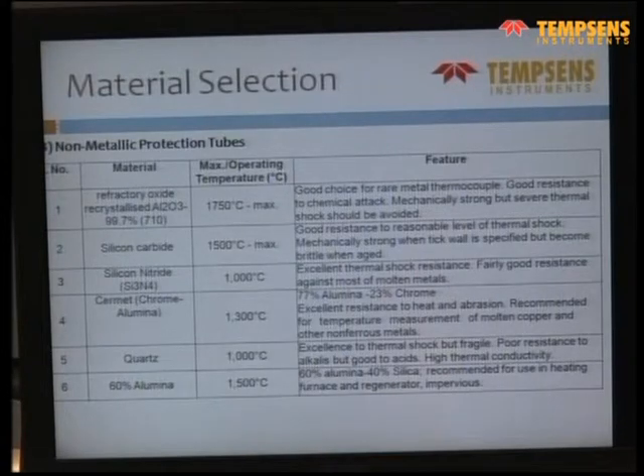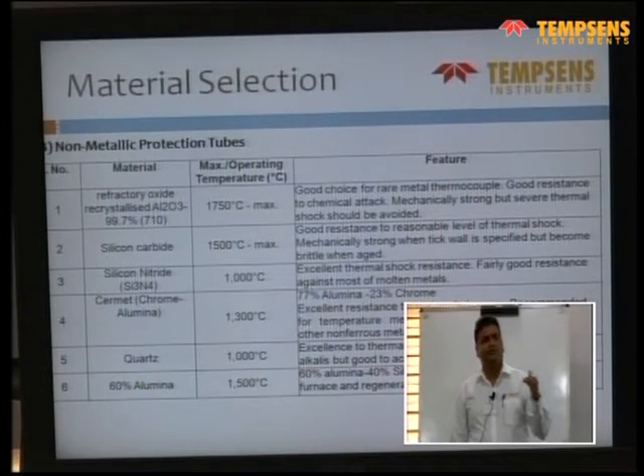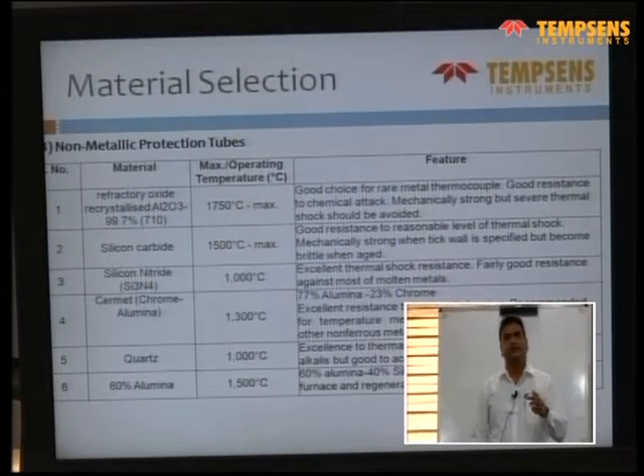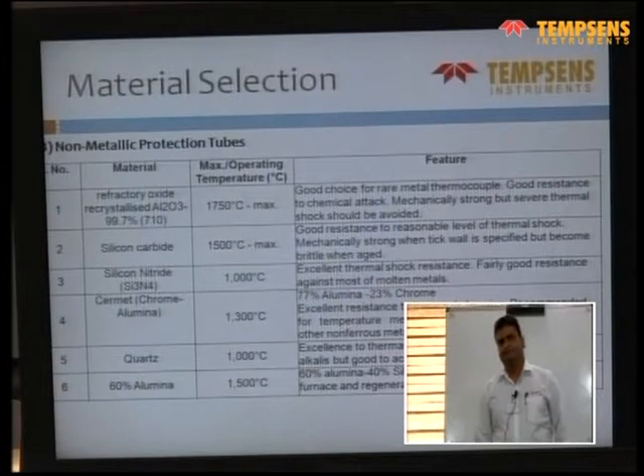Then coming to non-metallic, there are various kinds of non-metallic protection tubes which are available. The first one is the most common, which is called alumina. So this is 99.7% alumina, or it is also called C799 or 710 tube. So this has 99.7% alumina and is suitable up to 1750 degrees centigrade. And this is the most common tube which is used for all platinum thermocouples. So for all R-type, S-type, B-type thermocouples, this is the primary tube which is used. Even if you are using a combination with any other tube, the inner tube has to be this alumina tube.